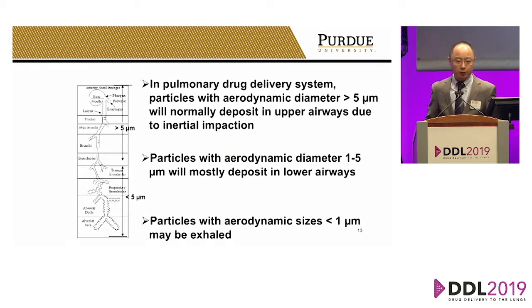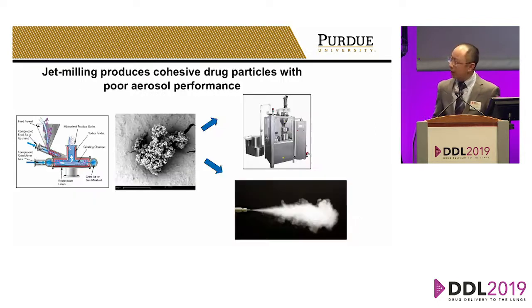Everybody knows this gold standard, 1 to 5 microns in aerodynamic diameter, we need to go to the deep lungs, or sometimes 1 to 3 microns. Anyway, we talk about particles of very, very small size. And usually these small particles in the industry are produced by jet milling. The problem is if you break these coarse particles into very tiny particles, you create new surface with high surface energy, with high electrostatic charge, and a very low mass. So they are very problematic, everybody knows. They grow to form agglomerates, lumpy powders. Very difficult to manufacture. Very difficult to put into capsules or blisters. And also very difficult to aerosolize, to be inhaled into the lungs.